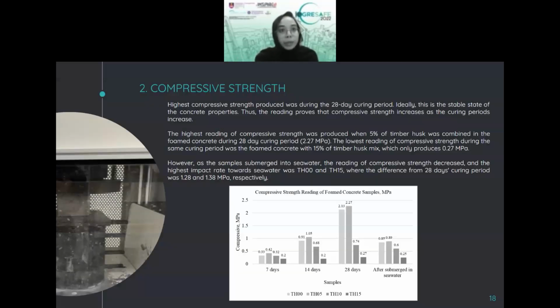Moving on to the second part, which is the compressive strength. The highest compressive strength was produced during the 28 days of the curing period. And this is justified by the stable state of concrete properties, because the 28 days of curing period is a stable state of the concrete properties. This shows that compressive strength reading increases as the curing period increases, as you can see from the graph. The best foam concrete is when we use 5% of the timber husk inside the foam concrete at the 28 days of the curing period, where the reading shows 2.27 megapascals. However, after being submerged in seawater, the reading reduces very rapidly. So this might be an option for better additives to be used.